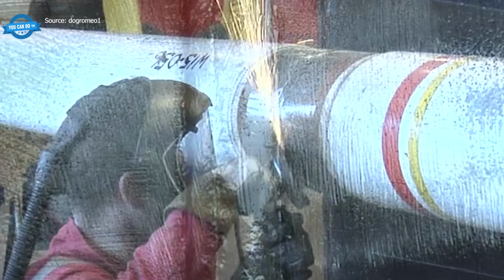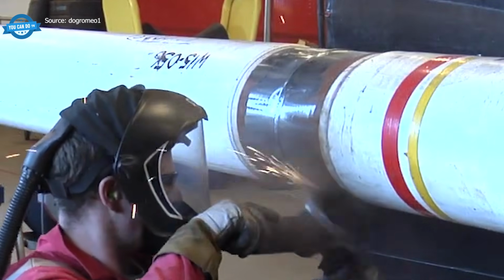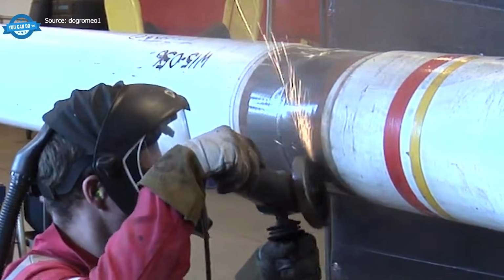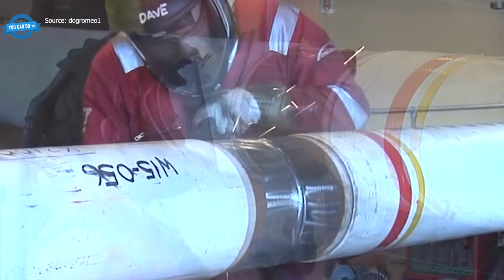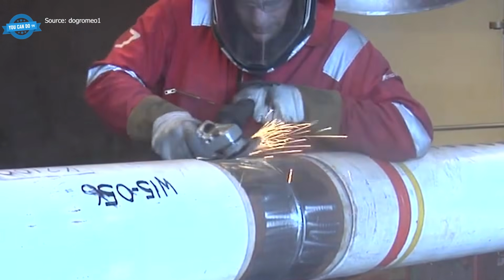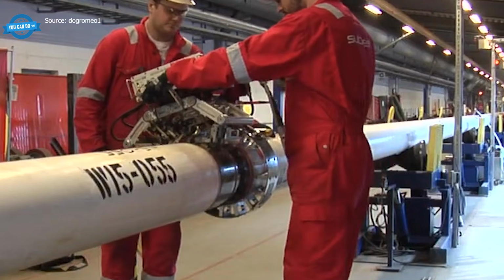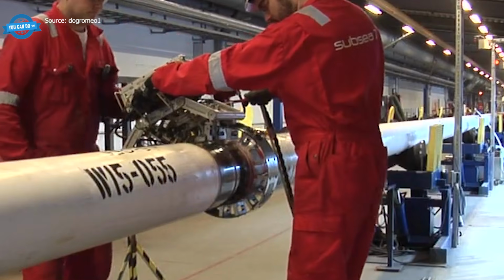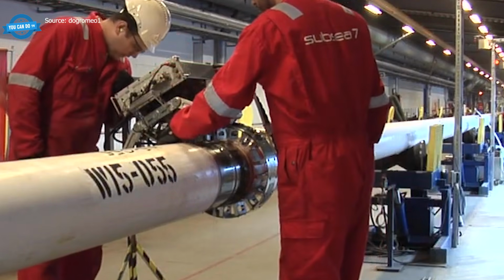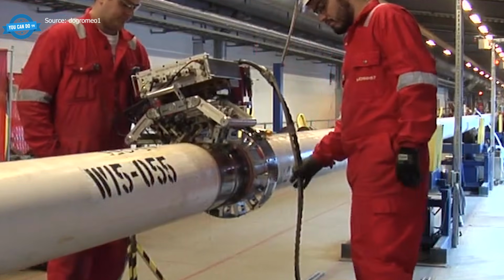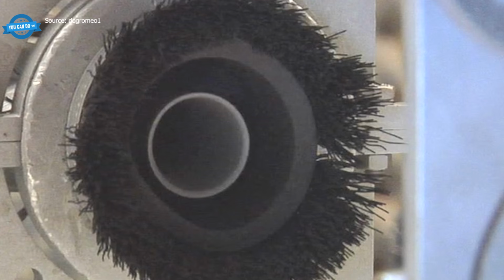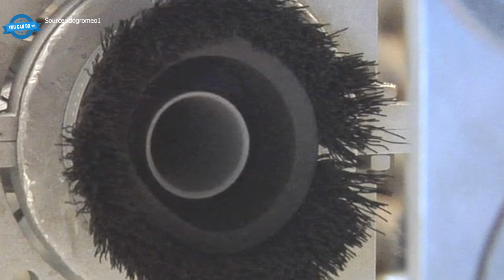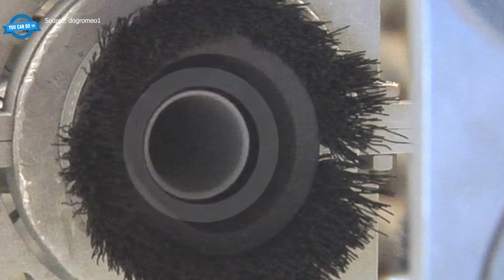Root pass, hot pass, fill passes, and cap pass are all welded together onshore, joining single pipe sections into continuous strings called stalks that are typically 1 to 2 kilometers long. Each weld passes through digital radiography or automated ultrasonic testing. The bare welded zones are grit blasted and protected with fusion-bonded epoxy and heat shrink sleeves for field joint coating, all while still on land.